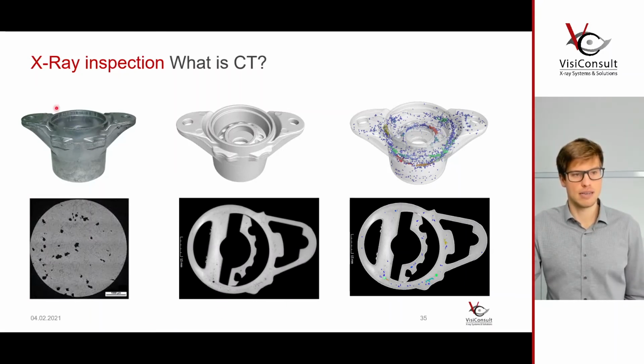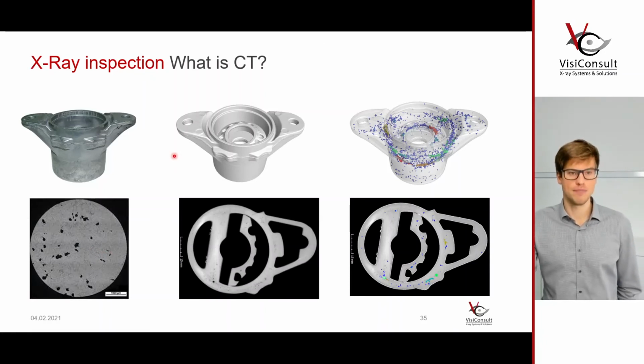And this is how it looks. You have the real part here. In this case, this is a casting part, but it shouldn't matter. It's just to show you the different results that you get. So on the casting part, of course, you can do a real cut. You can cut the part, look at the metallographic structure, and look for porosities, inclusions, cracks, and stuff like that. But with CT, you can create a three-dimensional model of the part. You can create the perfect digital twin of your part. And then you can virtually create cross-sections and perform analysis like porosity analysis, for example.